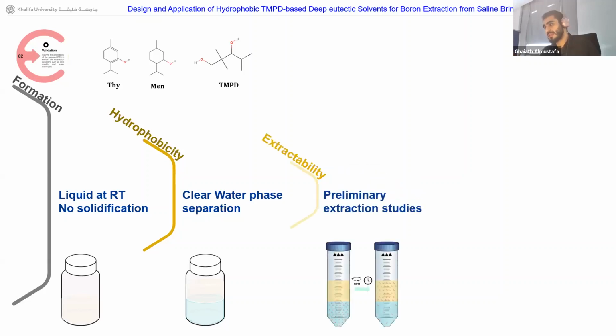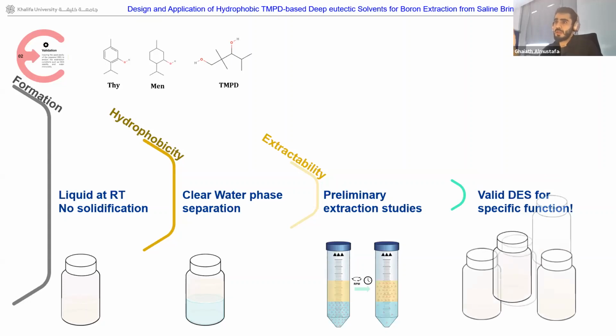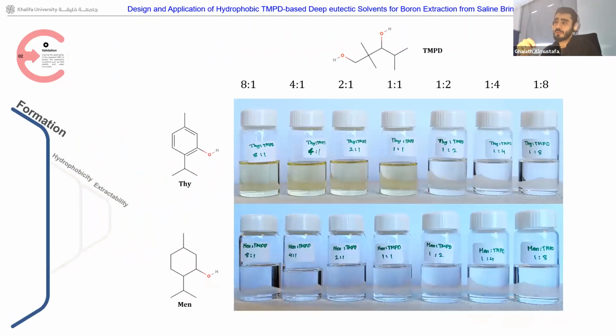Then we do some preliminary studies to prove that they are extracting boron, and then we end up with a valid DES for this specific function. Now, as for the formation step, we mix the TMPD with thymol or menthol in different ratios, starting from 8:1 up to 1:8. And you can see that they have been stable for quite a period of time.